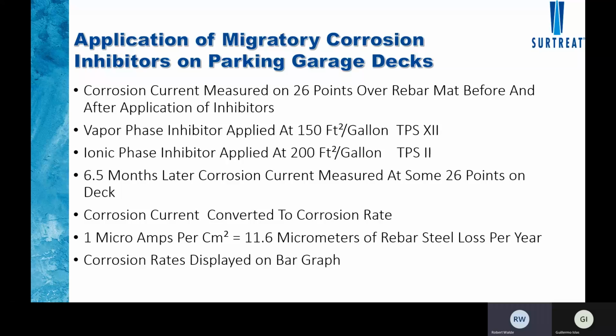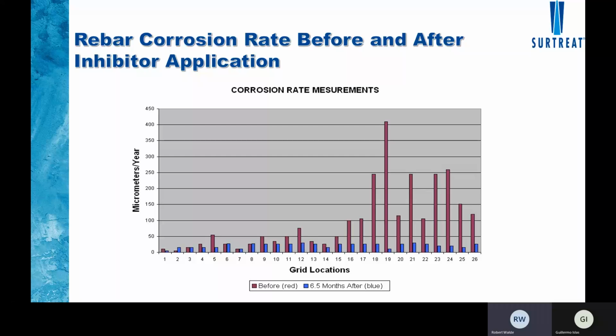We then waited 6.5 months and went back and redid these measurements at the 26 points using the Galvapulse. And what we're able to do is we take the corrosion rate, which is measured in microamps per square centimeter, and 1 microamp per square centimeter equals 11.6 micrometers of rebar steel lost per year, which is the real corrosion rate. And we can see these rates imposed where we're measuring the before, which is in red, and the after treatment in blue. What this shows is two very important things.